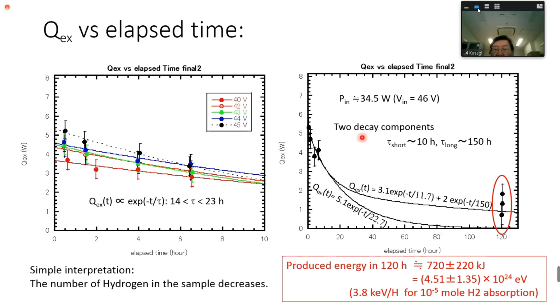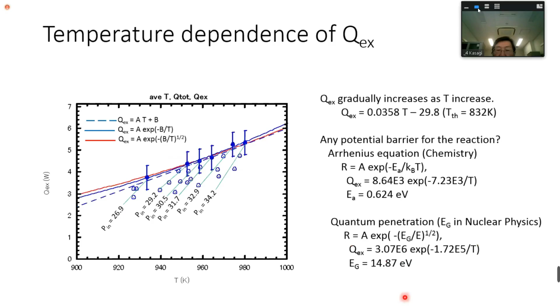And we can apply the 2 decay component like this. Then we can integrate all this region. Finally, we can get a produced energy in 120 hours of the order of about 700 kilojoule. This corresponds to about 4 keV per proton.